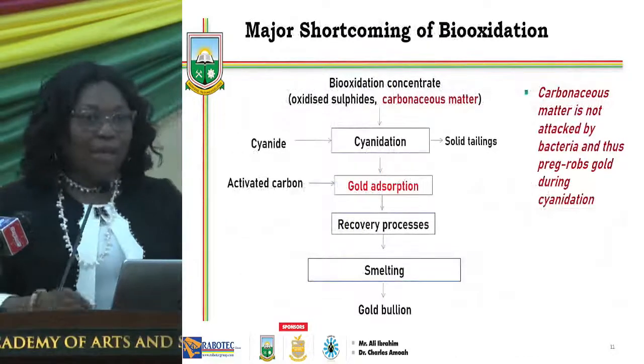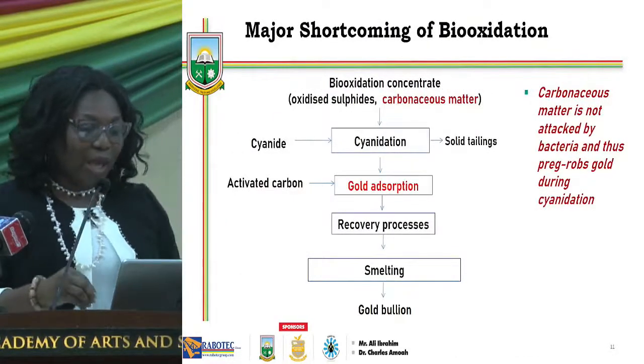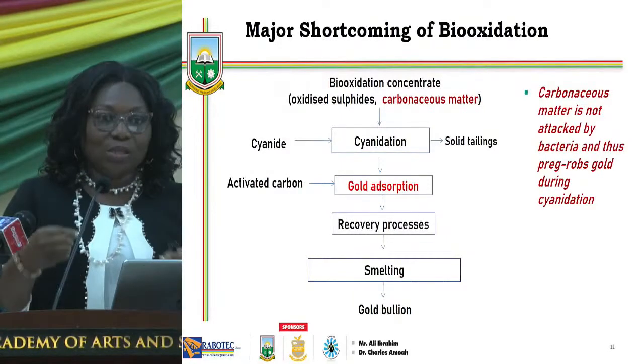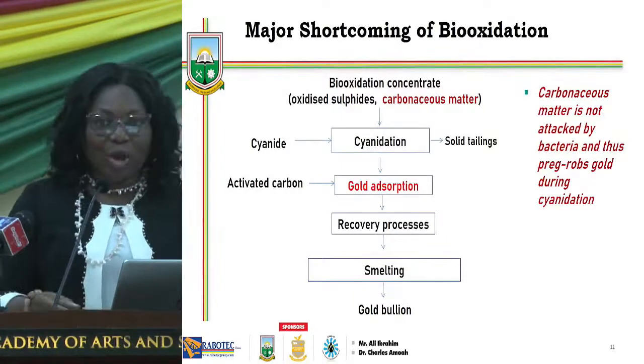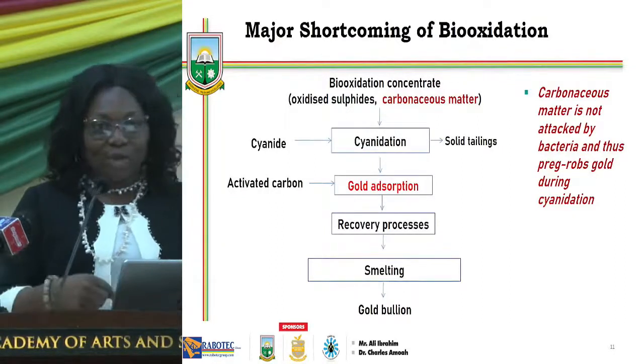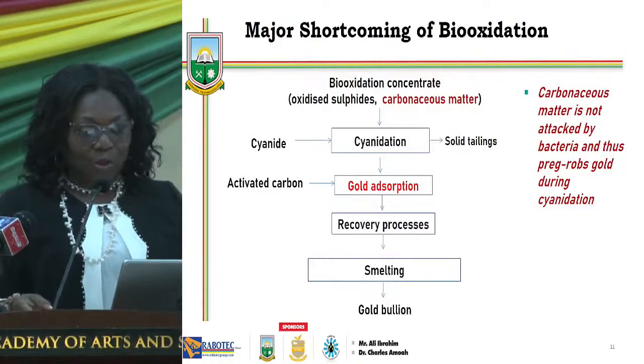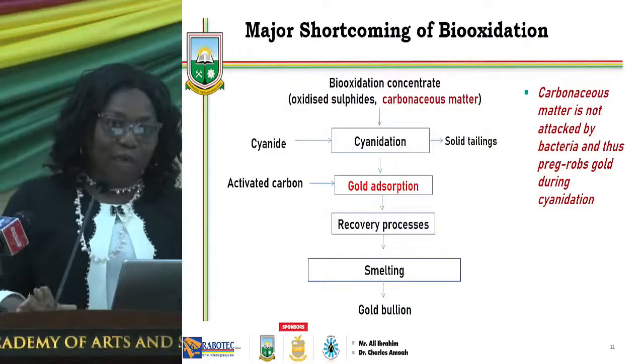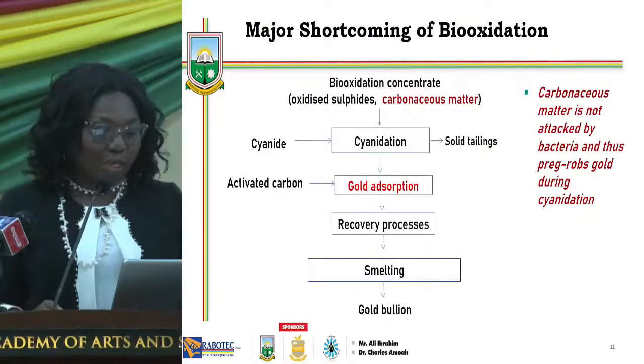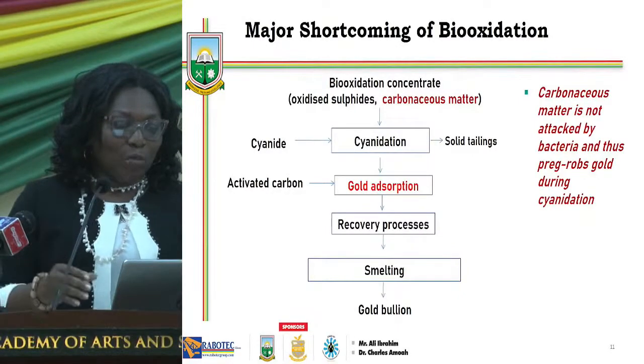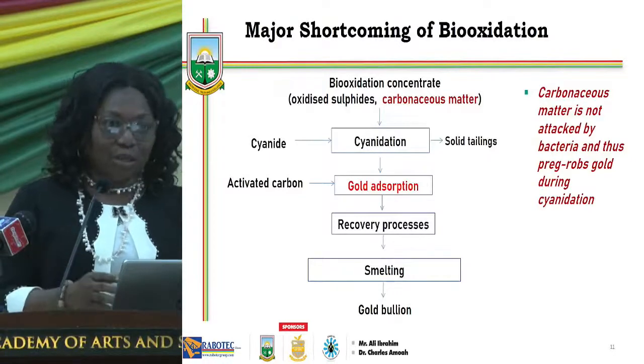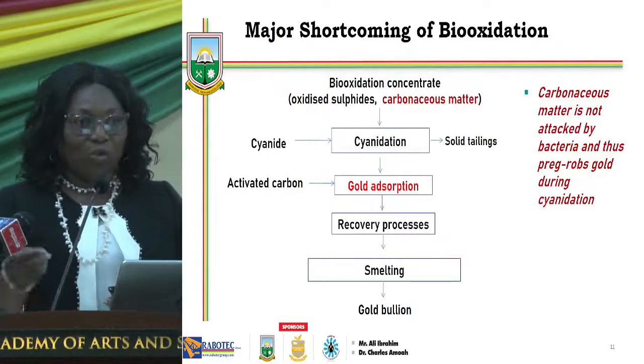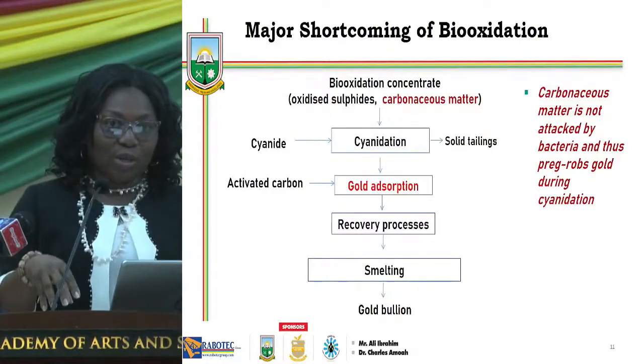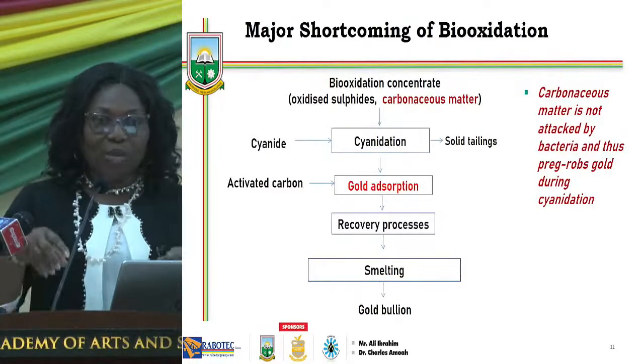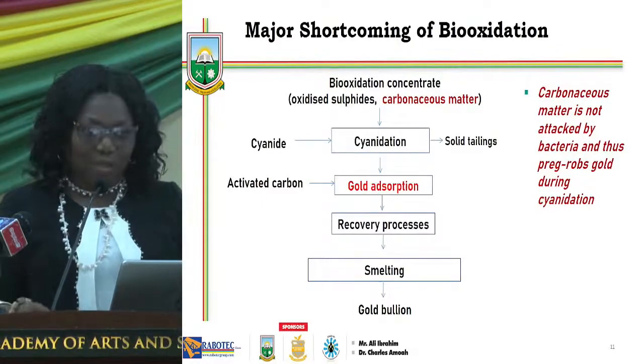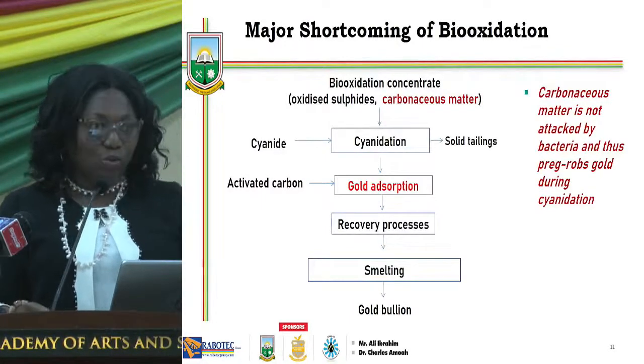All right. So at the end of biooxidation, we have the Biox concentrate, and that is the oxidized component of sulfide. But what happens? Because the bacteria do not use organic carbon, and the carbonaceous matter, they will finish their work, but they will not touch the carbonaceous matter. So when we send the Biox concentrate through leaching, where we dissolve the gold in cyanide solution, the carbonaceous materials are still part of the ore, and they will start taking the gold back into the solid. And that definitely will lead to losses.